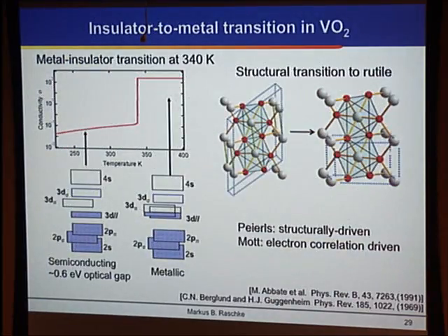And so the example I'm showing you is vanadium dioxide. What looks like a benign insulator at low temperature undergoes, at 340 Kelvin, a sharp first order phase transition into a metallic phase. And really, since the early discoveries of this effect about 50 years ago, there is still no clear picture whether it's a Peierls type mechanism, where you have a structural transition, because as you undergo this electronic change, there is a structural change of the lattice from a monoclinic to a rutile phase.